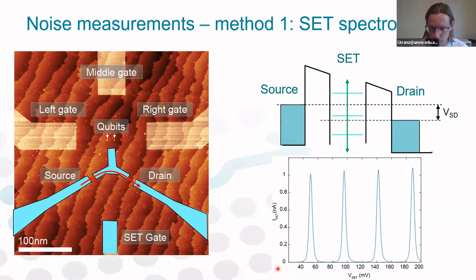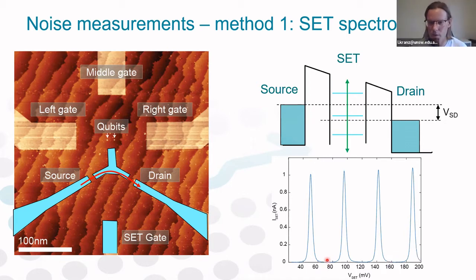And what I'm showing here at the bottom plot is current through the SET as a function of the voltage VSET. And this refers to the voltage applied to this bottom gate here. By applying voltage to this SET gate, we can shift the energy levels of the SET up and down. The regions where we see high SET current correspond to the situation where we have an energy level in between source and the drain energy levels that can facilitate the tunneling from source to drain. And regions without current correspond to situations where we have no available energy states and the SET is in Coulomb blockade.